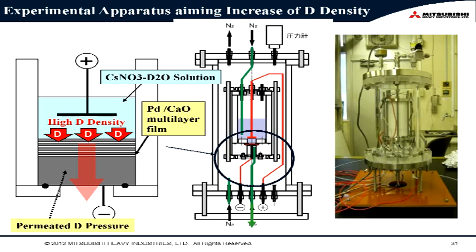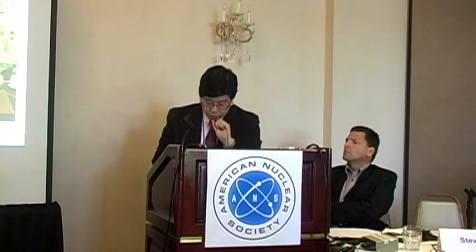because if we use this kind of configuration, we can control the deuterium density on the surface by the applied voltage. So if we apply a very large voltage, we will get a high deuterium density on the surface. So we use this kind of apparatus, and we are now performing many kinds of experiments.